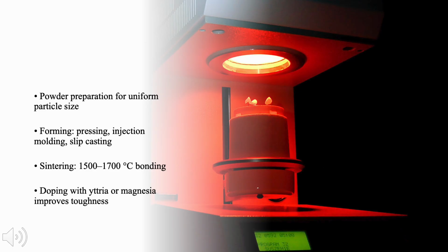To further enhance its properties, zirconia is often stabilized with small amounts of yttria, Y2O3, or magnesia, MgO. These stabilizers keep the crystal structure in its toughened phase even when cooled, preventing cracks and improving durability. The result is what we call yttria-stabilized zirconia, or YSZ, one of the most advanced ceramics known today. It's this stabilized form that becomes the foundation for everything from turbine coatings to dental restorations.